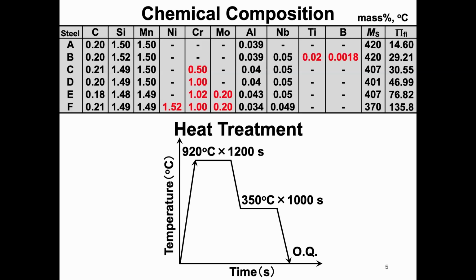describe the experimental procedure. In this study, 6 kinds of steels with chemical compositions as shown in this table are used. Steel A was base steel, and titanium, boron, chromium, chromium-molybdenum, and nickel-chromium-molybdenum were added to the steels B to F. Heat treatment was conducted by annealing at 920 degrees Celsius for 1200 seconds, followed by isothermal transformation treatment at 350 degrees Celsius for 1000 seconds to produce a TBM steel.